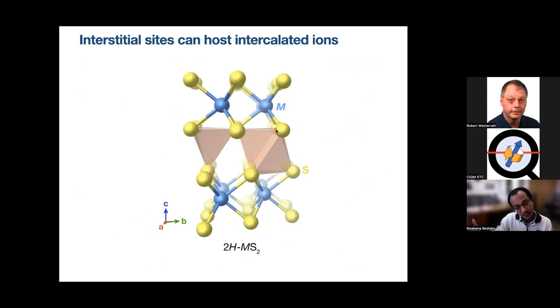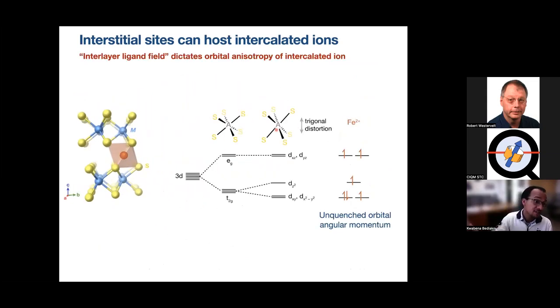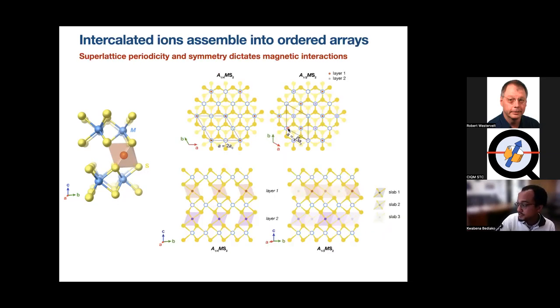Now, in my group, we try to design magnetic materials by looking at the interstitial sites. So from my time in Philip's group, I have a strong bond, pardon the pun, with intercalation chemistry. And it turns out if you can get magnetic intercalants in between the sheets of materials, then the ligand field or crystal field around that paramagnetic ion can lead to some unquenched orbital angular momentum that then can lead to long range magnetism if these magnetic centers can be strongly enough coupled together.